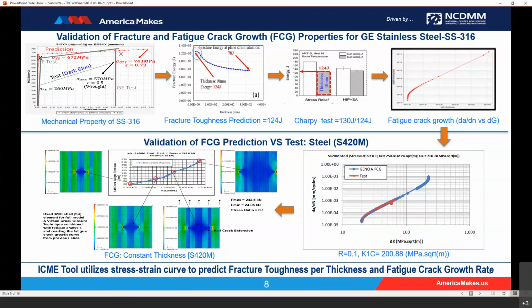In sum, we are confident that our assumptions for not only fracture toughness prediction but also fatigue crack growth rate will be applicable and will be validated. ICME tools utilize stress-strain curves to predict fracture toughness per thickness and fatigue crack growth rates.